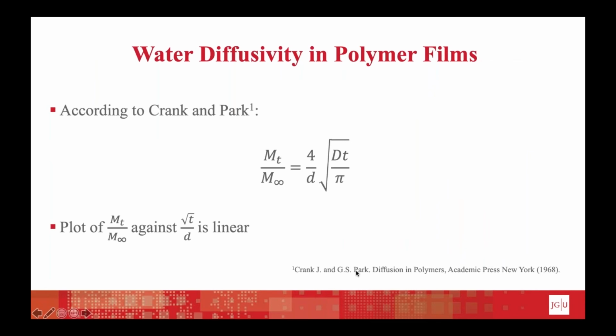According to Crank and Park, we have the following formula, which is valid for as long as M_t divided by M infinity is smaller than 0.4. In this case, M_t is the mass of our sample at time point t, and M infinity is the mass of our sample at equilibrium at a given relative humidity. d, the small d here, is the thickness of our polymer film. The large D, or capital D, is the water diffusivity.